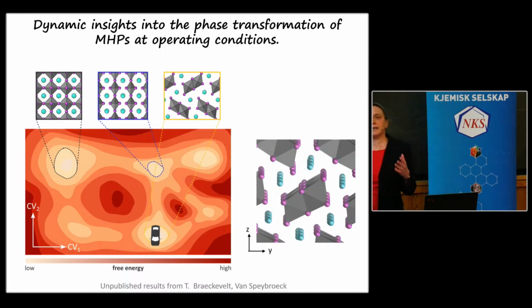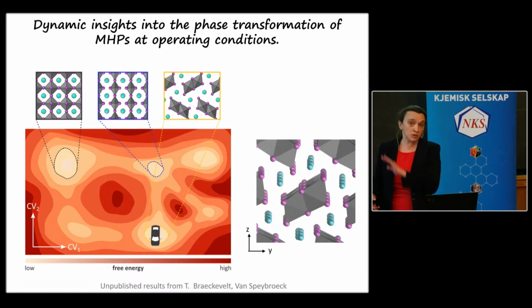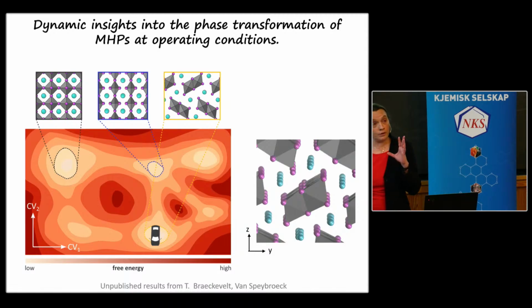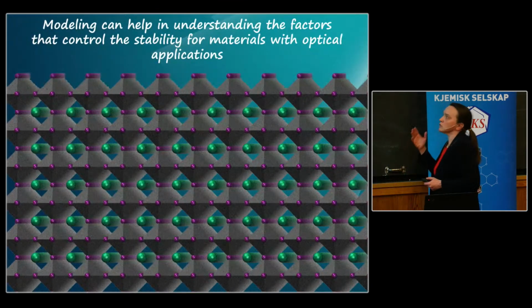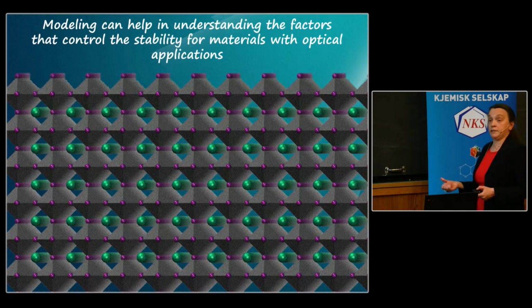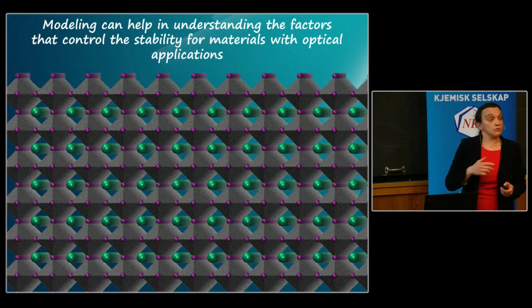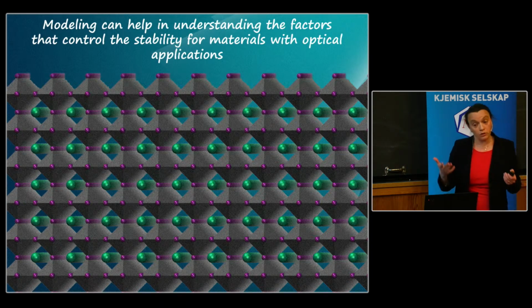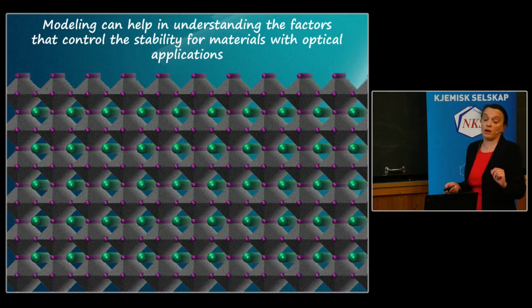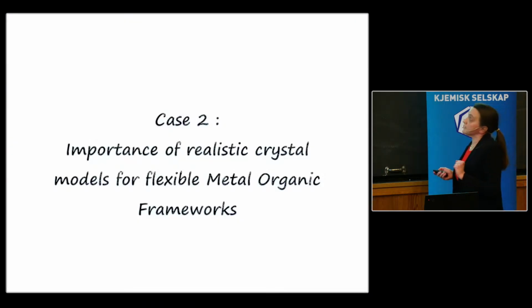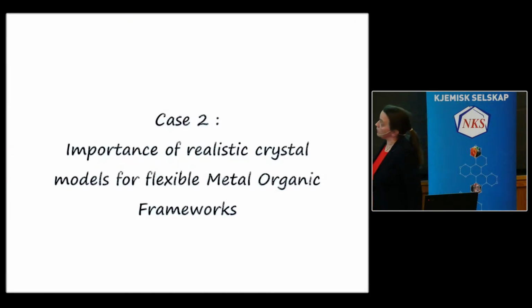Yeah? So by doing these molecular dynamics simulations, we can try to unravel how this process brings us from one state to the other. It looks very simple here, like I presented here, but it's really a huge challenge to find good coordinates and find good paths to lead you to all these minima, because there are many, many minima for this material. It's really not fully resolved. So this is the first example where you can see operating conditions are important, and you can also try to understand what happens and try to tune the material for interesting applications in close synergy, I would say, with experimental people.